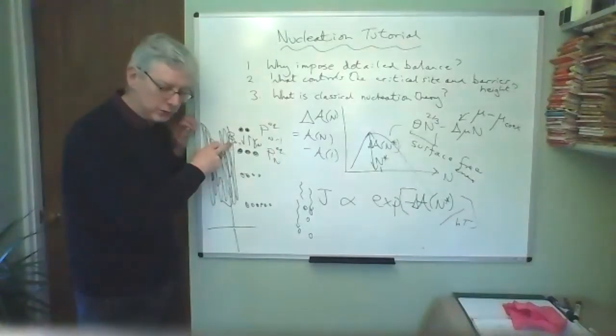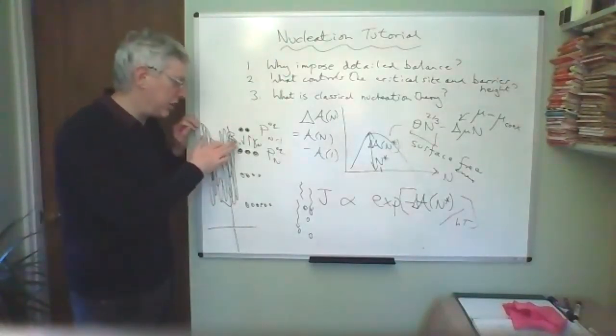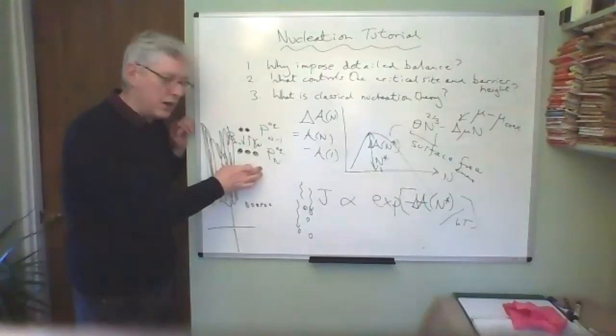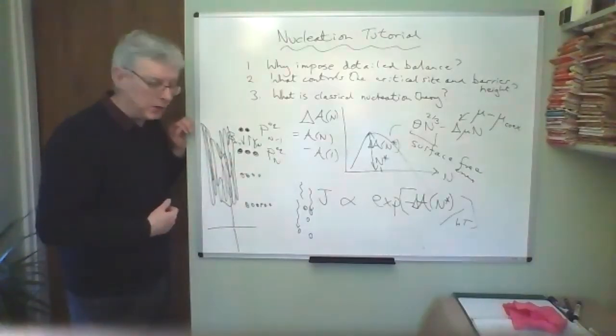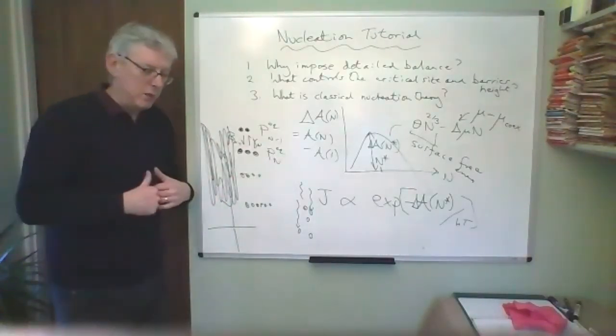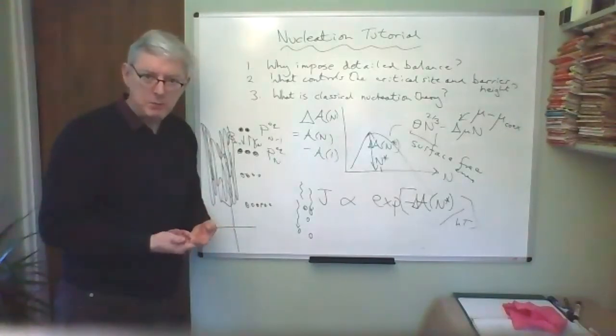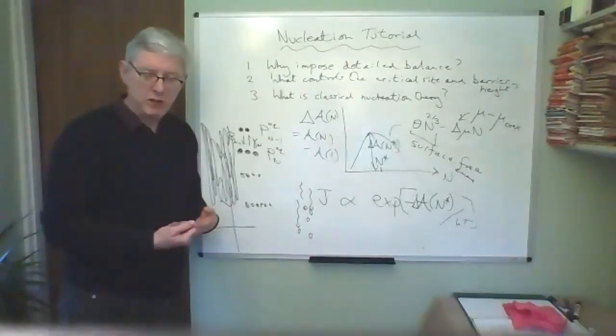We essentially, I haven't said this explicitly, say, let us imagine when out of equilibrium that all the evaporation rates are the same, but the growth rates are made bigger by virtue of the gas being supersaturated, being overpressurized.